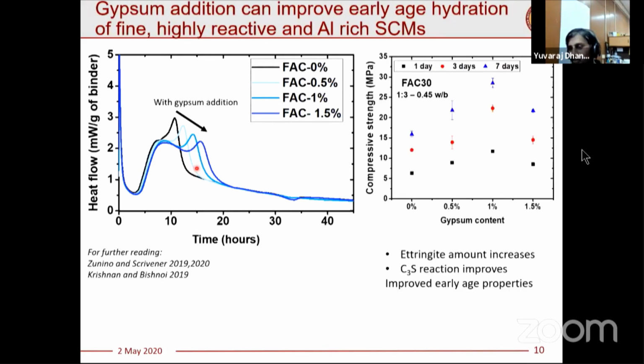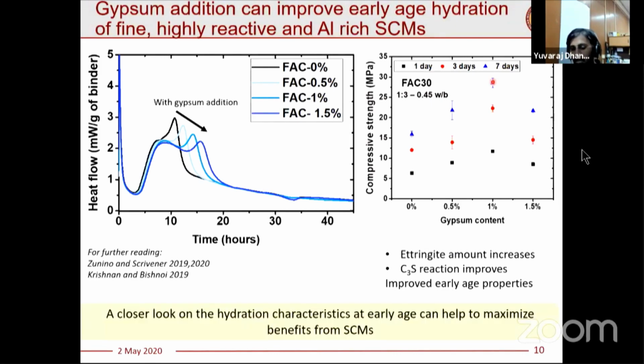So when this happens, we do a small mortar bar strength test. You can see the strength test without gypsum, and when you start adding gypsum to it, because we are allowing the clinker reaction to happen properly, and the ettringite amount can get increased because of the addition of gypsum, 7-day strength can change from nearly 15 megapascal to around 25-30 megapascal. So by taking a closer look at the hydration characteristics, we can maximize the early age benefits from some of these SCMs. Of course, not all would have reactive aluminate, but the one which has reactive aluminate or reacts much faster should be looked at much more closely, and the binder composition should be fine-tuned.